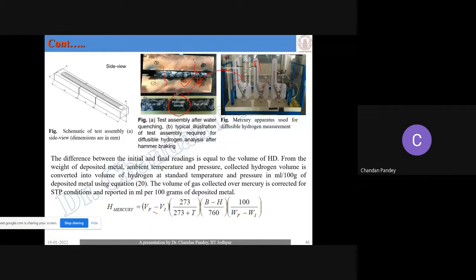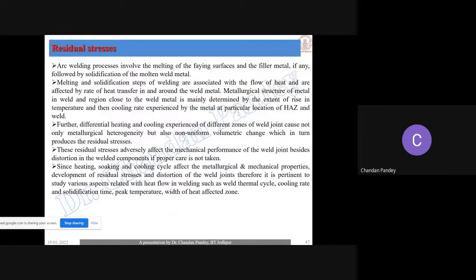Generally, to optimize the parameter, we consider the weld bead geometry, especially the depth of penetration and bead width. But if the diffusible hydrogen content or hydrogen-induced cracking is the major criterion, then for different parameters we perform the diffusible hydrogen content measurement, and the parameter that provides the minimum diffusible hydrogen content we consider the optimum one for the next process, or you can say for the multi-pass welding process.